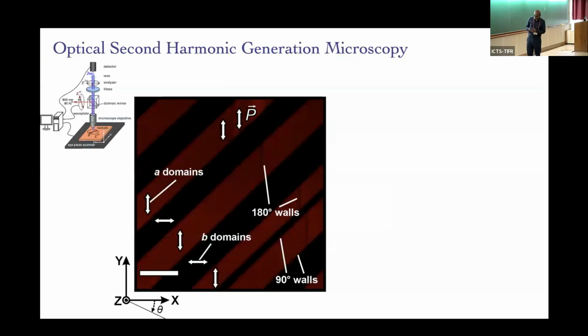But as soon as you start, so we developed this second harmonic microscope. What is that? It's just a fancy way of saying we come in with a laser of one color, in this case 800 nanometers, focus it, and detect twice the frequency, which is 400 nanometers in wavelength, double the frequency, half the wavelength, right? So we come in with, say, red or infrared light, and go out with blue.